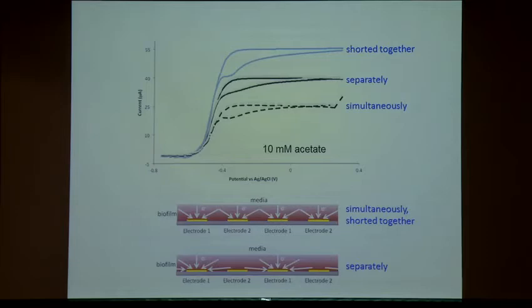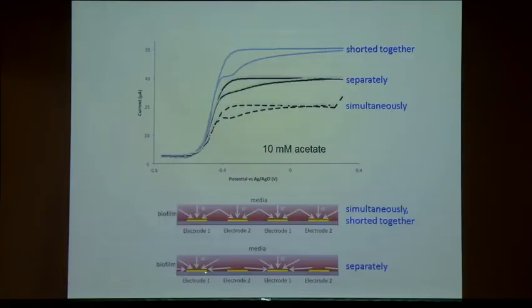So there's two quick experiments I can show you that we do here. The first is the catalytic voltammetry, where all the electrodes are shorted together, and the arrows here are representing the flux of electrons from acetate oxidation on the biofilm towards the electrode surface. And I get this classic catalytic voltammogram here. If I actually separate them using a bipotentiostat, so I can measure the current going into this electrode and all the other ones comprising electrode 1, separately from electrode 2 and all the bands comprising electrode 2, that's what I get here. If I sweep them simultaneously, that's what I get here. And the sum of these two curves equals that.